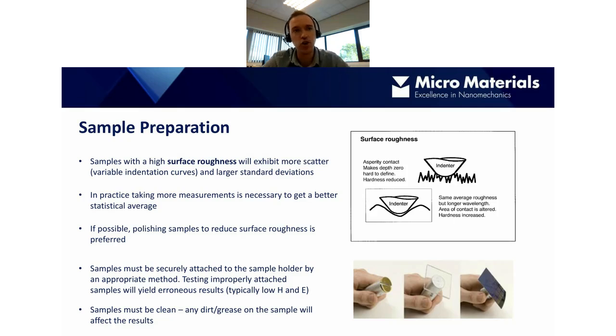If this is the case, then generally speaking, in practice, we would take more measurements to get a better statistical average. Of course, polishing the samples is preferable as well, if possible, because occasionally the act of polishing may change the mechanical properties itself, so it's not always desirable to do that.